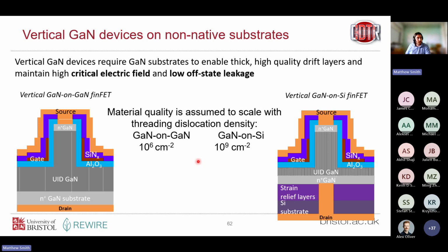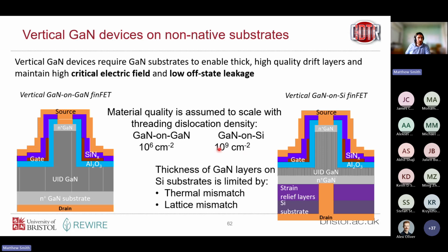So in terms of material quality, GaN on GaN has around 10^6 dislocations per centimeter squared, and can go down even to 10^4. GaN on silicon is somewhere around the 10^9 region, so about 1,000 times more dislocations per area in GaN on silicon that we have to contend with.